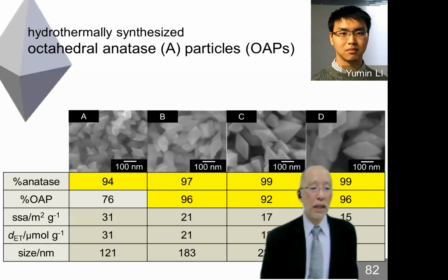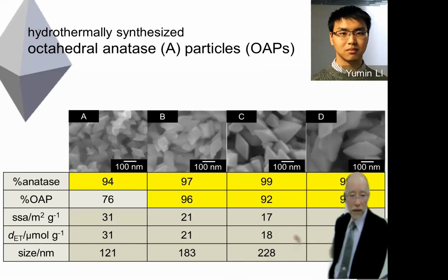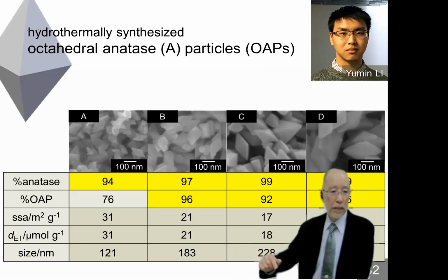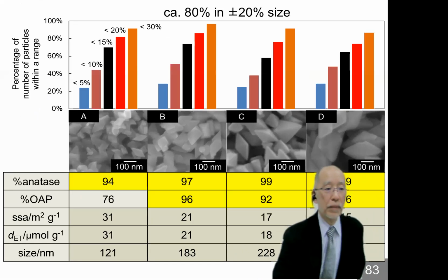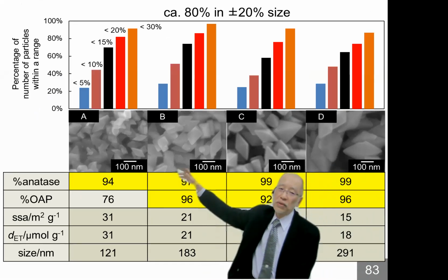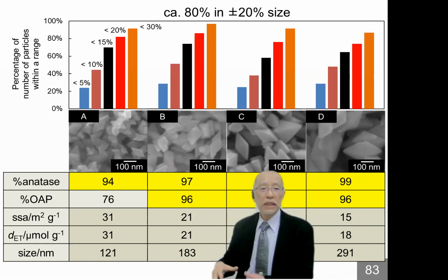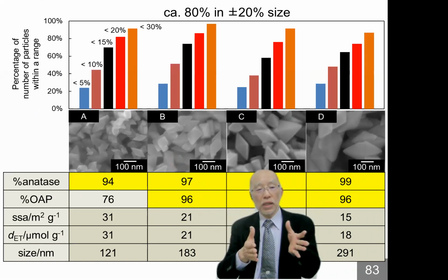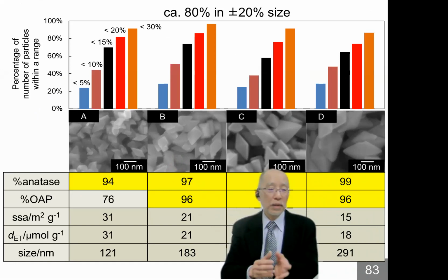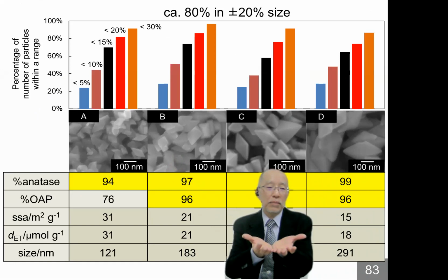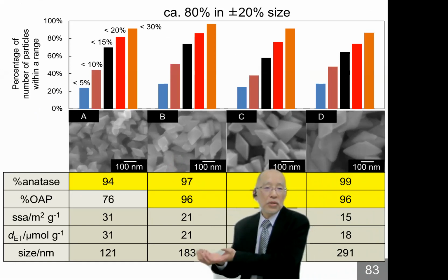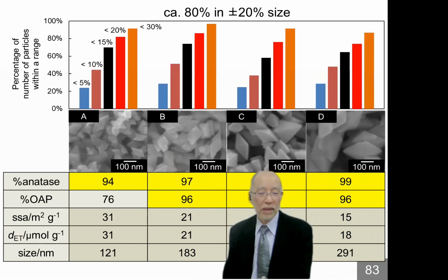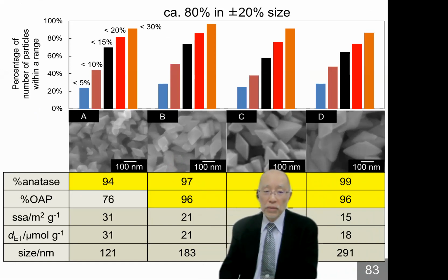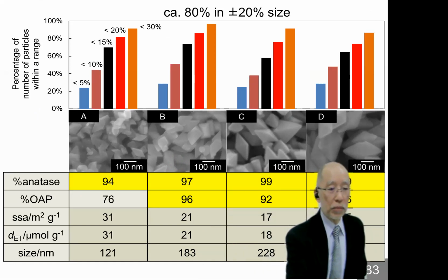Then that is like this. And okay, the particle size distribution is not so good, but actually we can say that the particle size within 20%, the distribution is about 80%. More than 80% of particles are in the range of plus minus 20% in size. Not so good, but not so bad. Almost the same particle size can be obtained.